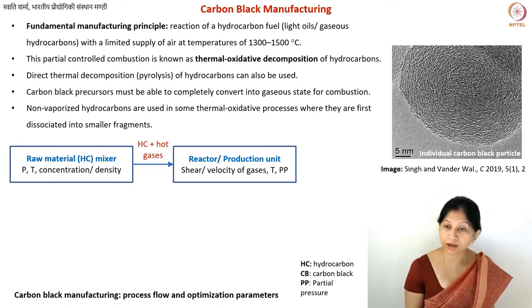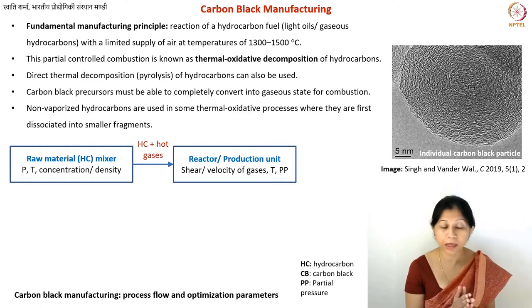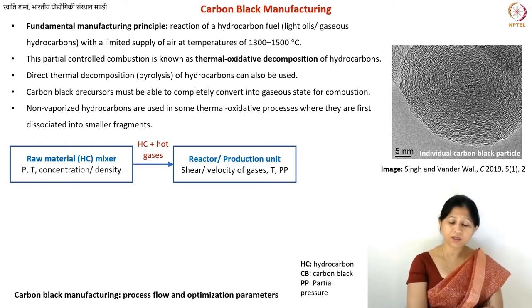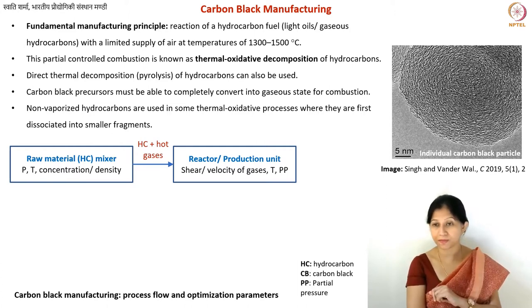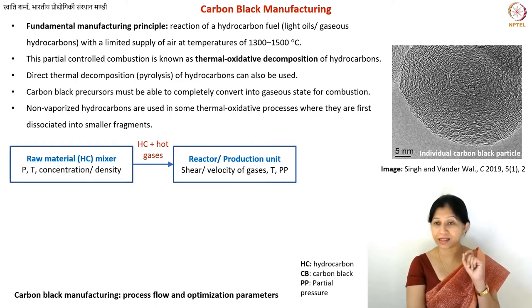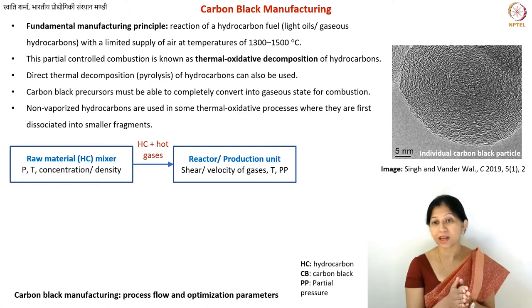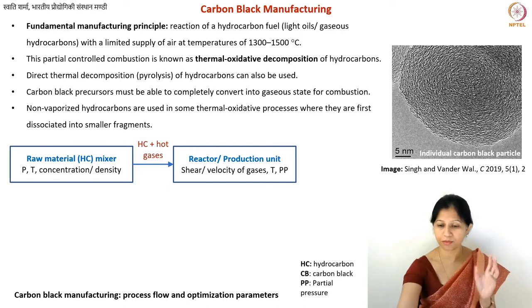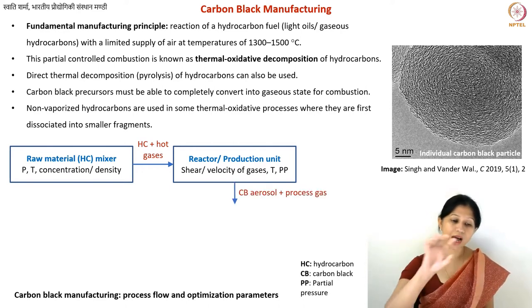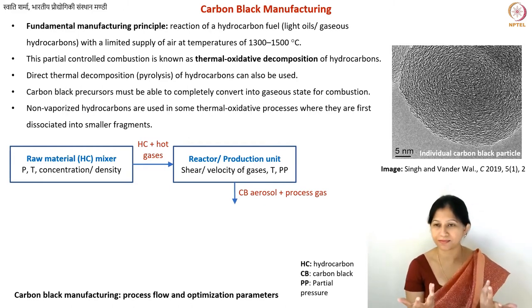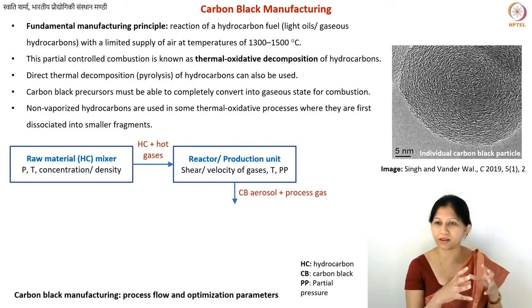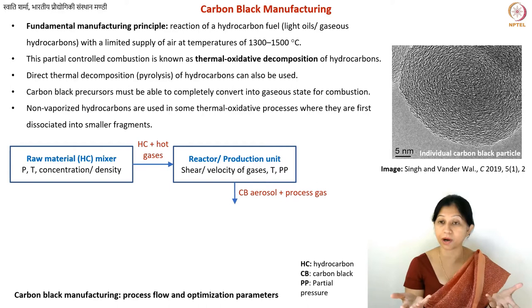The shear forces between gases and the velocity of gases also needs to be optimum. When using small hydrocarbon gases as your fuel, you may not need a separate mixing chamber, although in most cases you do. In the reactor itself you can ensure proper mixing, or you can use pre-mixed fuel. What comes out is carbon smoke — practically smoke — but the particles in the smoke are very well defined because the fuel was uniformly distributed and the fuel particles were very small. So you have well-defined carbon particles in the form of a carbon aerosol.